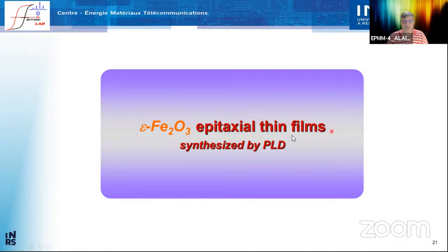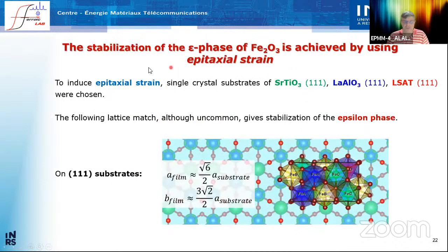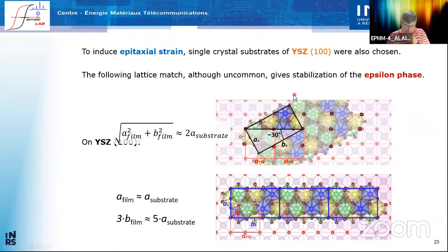So what about epitaxial thin films? Epitaxial thin films on 111 oriented perovskite substrate, and we show 3 different substrates here in order to modulate, to change the epitaxial strain, give a very complex epitaxial relationship, which looks like this. You see the 111 plane of the substrate behind, and you see the perovskite. So you see the epsilon ferrite on top, and this is on 111 oriented perovskite substrate, or on 100 YSZ, you have an even more complicated epitaxial relationship, which you can see here.